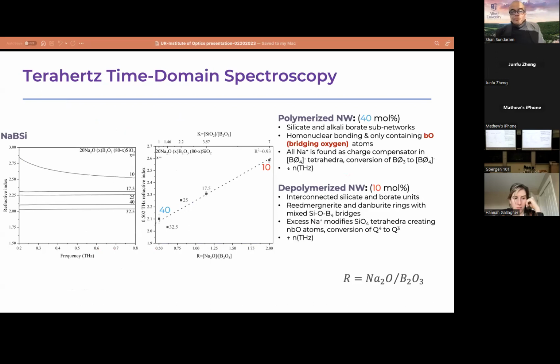So now a snapshot. I'm only showing you partial results. This is a family of borosilicate. We are showing you refractive index in the terahertz range we measured. And correspondingly, we are showing you how we pick one terahertz value for 0.5 terahertz refractive index, how it changes with the R values, which is the ratio of alkali to B2O3. You can clearly see a more or less very strong linear relationship with most of the compositions. And clearly this says by changing glass chemistry in this family, I can actually vary the terahertz refractive index and also absorption coefficient. Sometimes I'm showing mostly refractive index data, but we also have absorption coefficient data from the same data set.